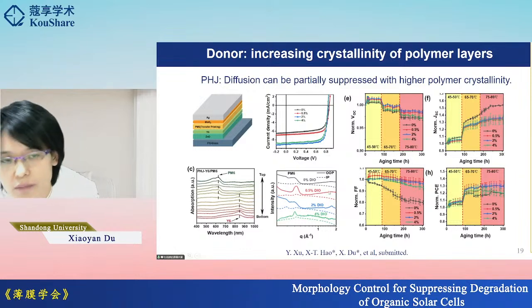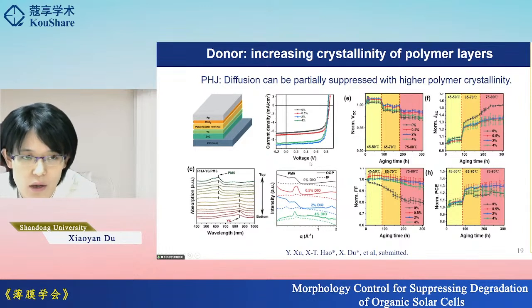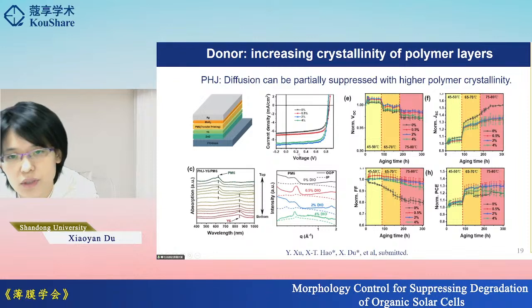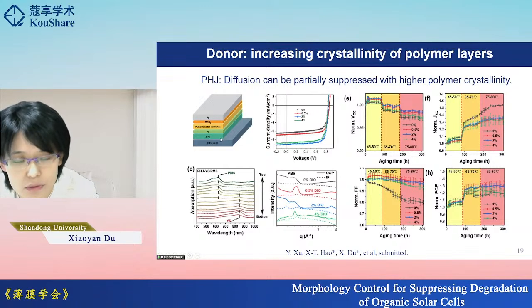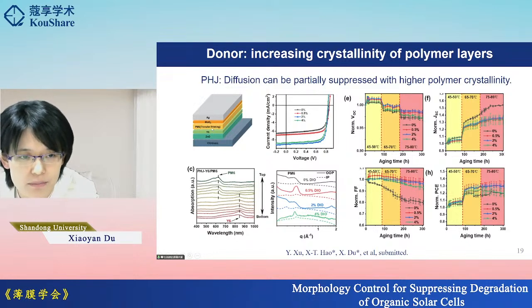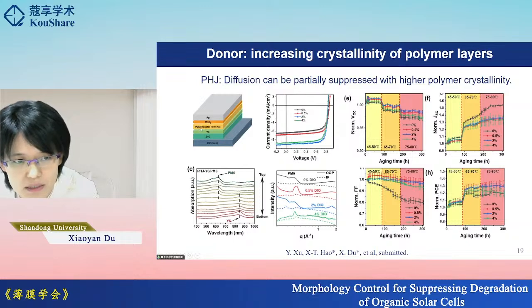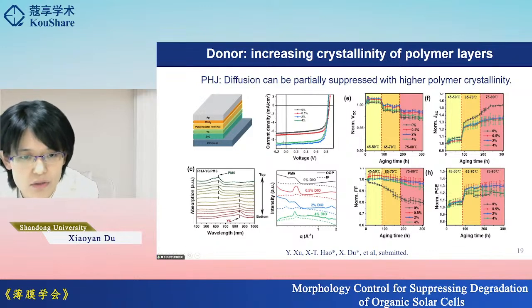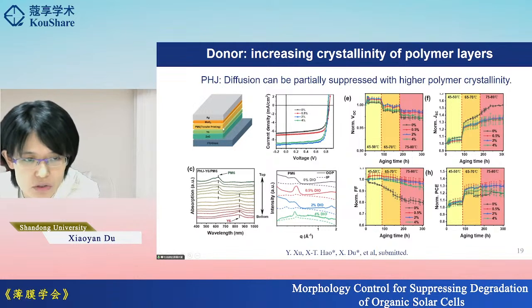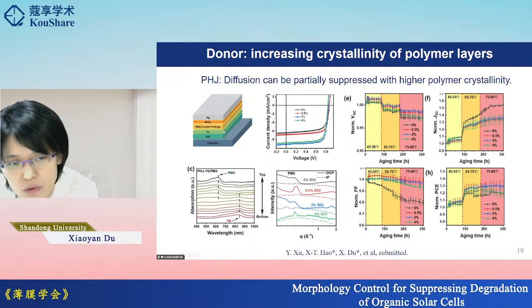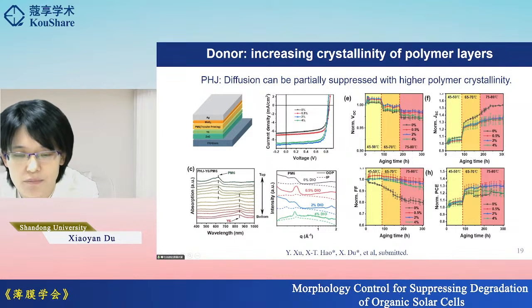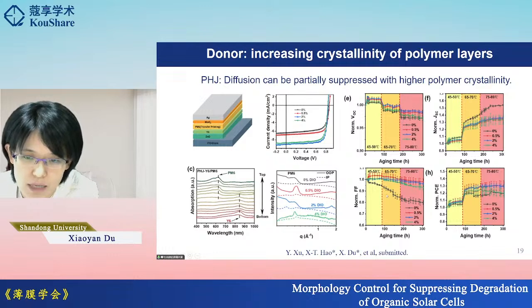Okay, so far I have only talked about the non-fullerene acceptors, and what about the role of the polymer donor in the stability of the solar cells? Here we show an example where we use a planar heterojunction or bilayer structure to investigate the influence of the crystallinity of the polymer donor layer on stability. For this transfer-printed PM6, the crystallinity is controlled by adding additives. Although the device performance is not high due to the bilayer structure, we can use this well-controlled morphology to study the stability. Here shows the thermal stability of these bilayer devices.